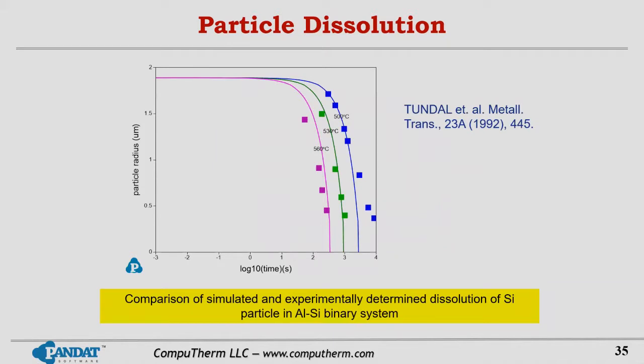And I think particle dissolution is one of the important applications for diffusion simulation, because basically we can calculate how particles formed during solidification, and how they dissolve during the homogenization treatment. So you can optimize the homogenization temperature and time, so you can dissolve these particles quickly and also save energy.